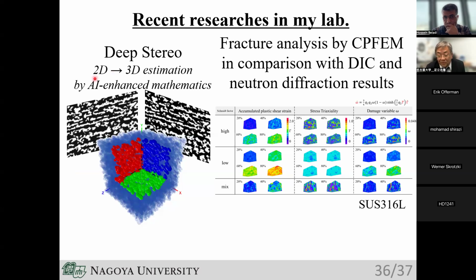Parallel to this, we are investigating the accuracy with which fracture initiation sites in metallic materials can be predicted. By integrating the crystal plasticity finite element method, CPFEM, digital image correlation, and the stress partitioning data obtained from the neutron diffraction, we seek to travel back in time to find out the crack initiation site, to understand the characteristics of the initial microstructure that led to fracture. We are also exploring the integration of deep learning-based image analysis into the temporal reconstruction process.